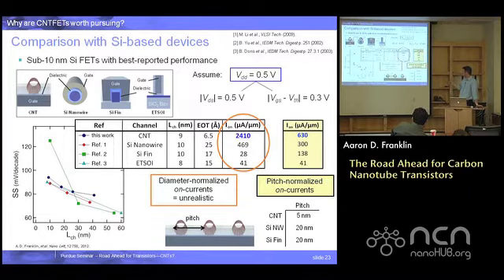If you had nanotubes at an aggressive 5 nanometer pitch, nanowires and fins at a mostly unrealistic 20 nanometer pitch, because you still have to fit all of their gate stacks, whereas the nanotube works just as well in terms of the gating with a single gate below it. So I'm not limited by the gate stack fitting in. And this is where it looks with pitch normalized current. The nanotube is still more than double what you can get out of the nanowires. So it's still great, but it's also a bit more realistic for what I could expect at a low operating voltage from the nanotubes. And it's promising.